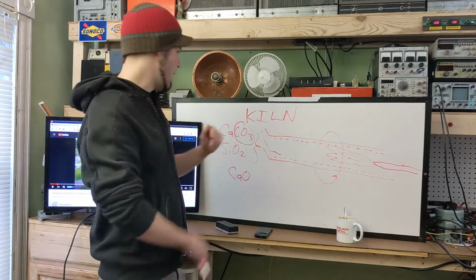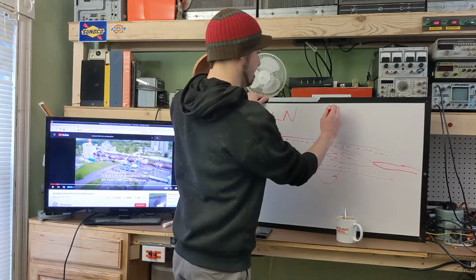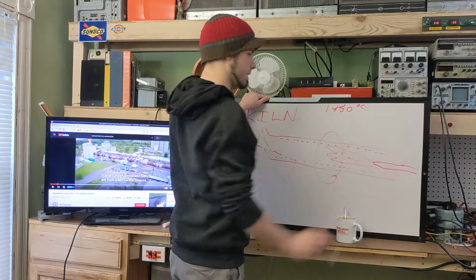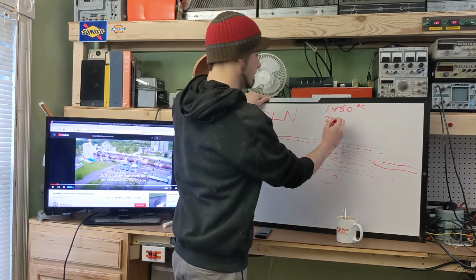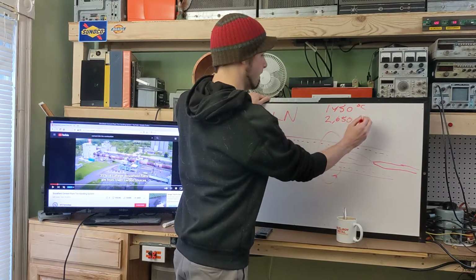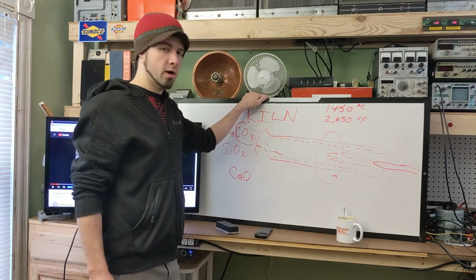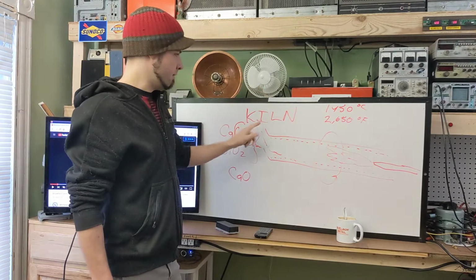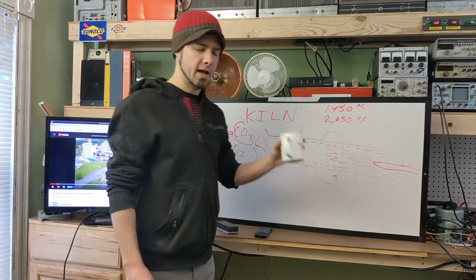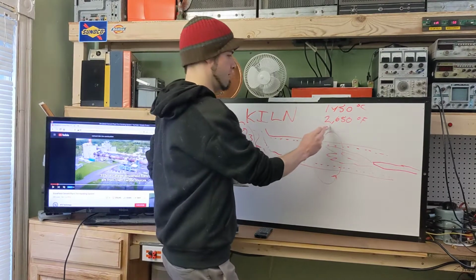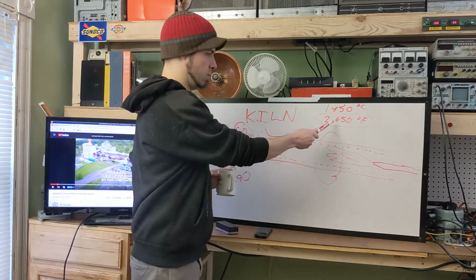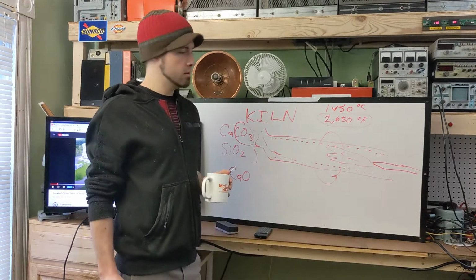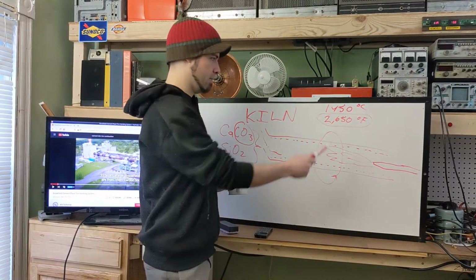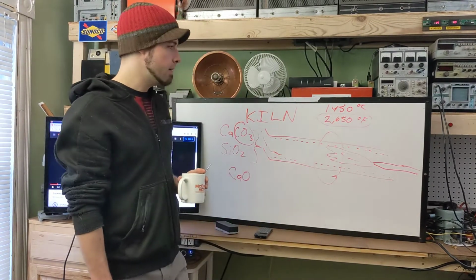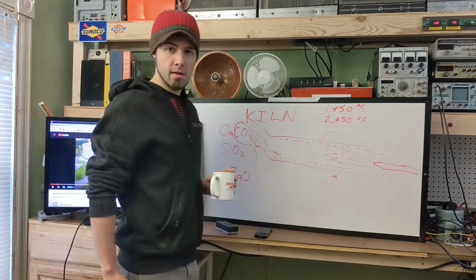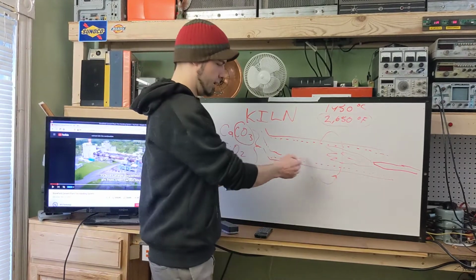Cook our pizza, right? No. This kiln operates at 1450 degrees Celsius, which is about 2,650 degrees Fahrenheit. That's quite a bit hotter than the oven in your kitchen. It's even hotter than the kilns we used to fire our clay pots in art class. This is extremely hot. That actually is within the range of the melting point of steel. Okay, steel, depending upon the alloy, melts between 2,500 and 2,800 degrees Fahrenheit. This kiln is operating in that temperature range. This is so hot, we could melt steel in here.